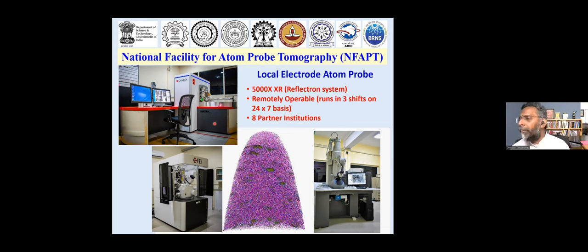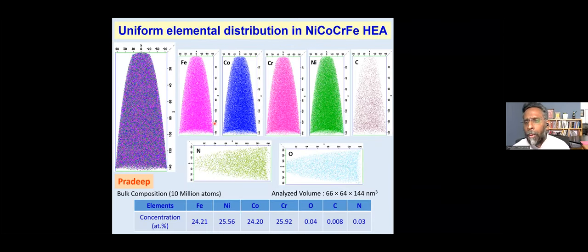And with this kind of machine, if I put one such high entropy alloy, this is nickel, cobalt, chromium, iron, four elements with 25% each, into an atom probe and look at how the elements are distributed, you will see such a uniform distribution of iron, cobalt, chromium, nickel. There is nowhere any segregation. So it's wonderful, at the atomic level, they're all uniformly distributed.